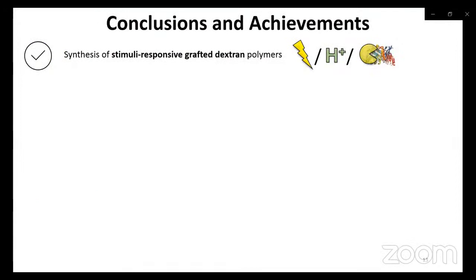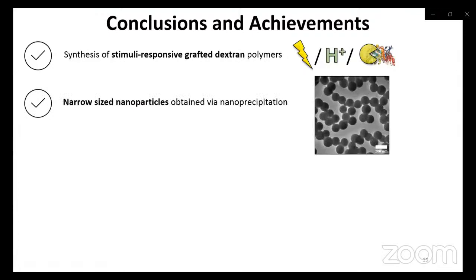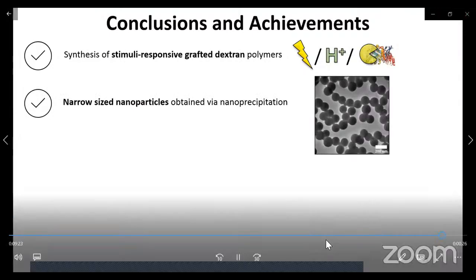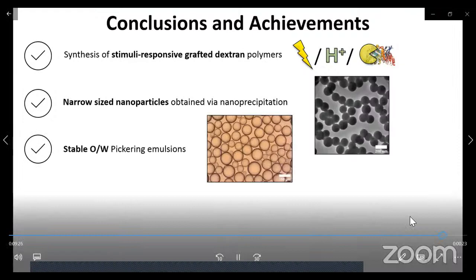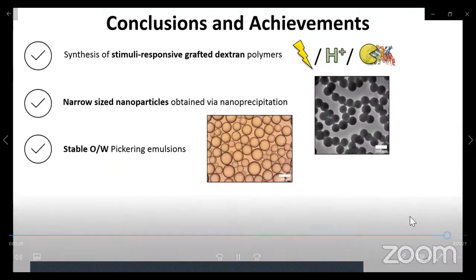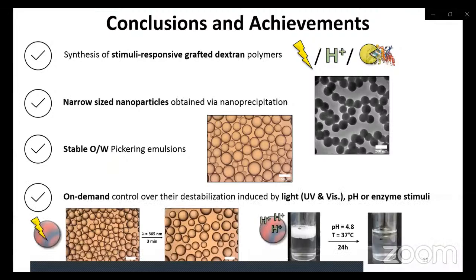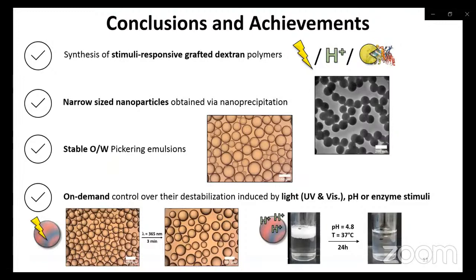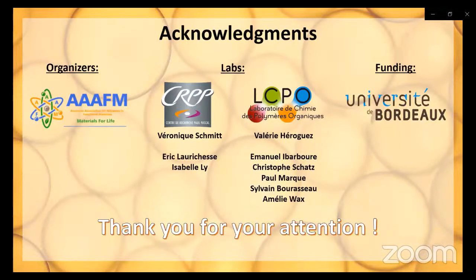Finally, we were able to synthesize stimuli-responsive graft dextran polymers, which are sensitive to light, pH, and enzyme, to produce narrow-sized nanoparticles through the nanoprecipitation process, to stabilize oil-in-water Pickering emulsions with long-time stability, but also to be able to destabilize them on demand thanks to light, UV and visible light, pH, or enzyme stimuli, with different kinetics, but still with good promising results. Thank you for your attention.